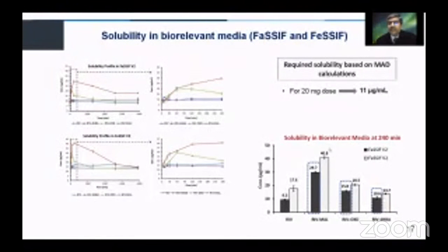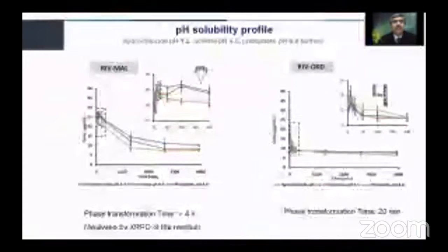And from this, it is apparent that the malonic acid is giving us the highest water solubility, and hence could be a probable candidate for further development. However, we must ensure that in an attempt to improve the solubility, properties like hygroscopicity are not being compromised. So in the subsequent slides, we will evaluate the other pre-formulation parameters of these co-crystal candidates.